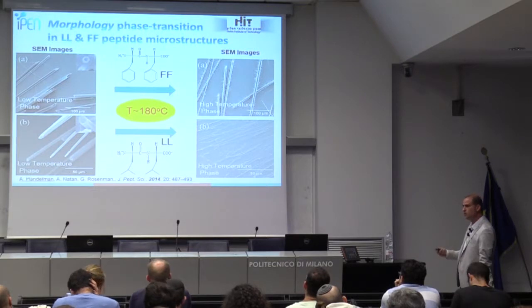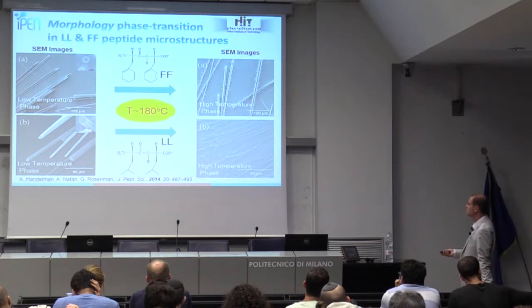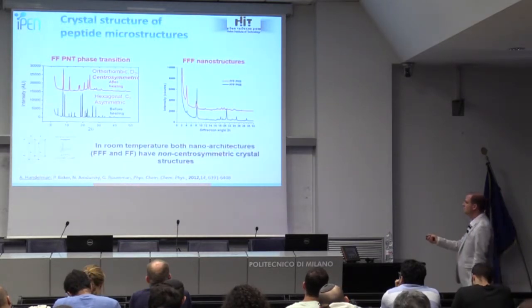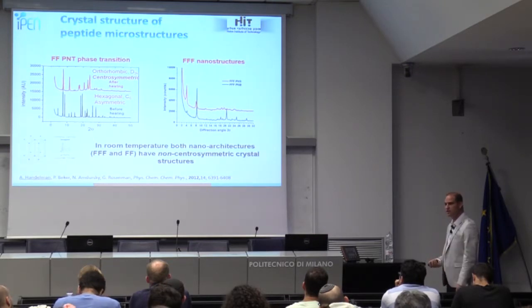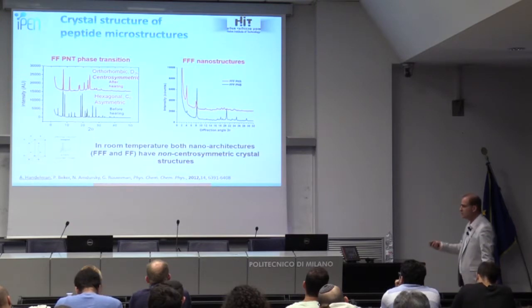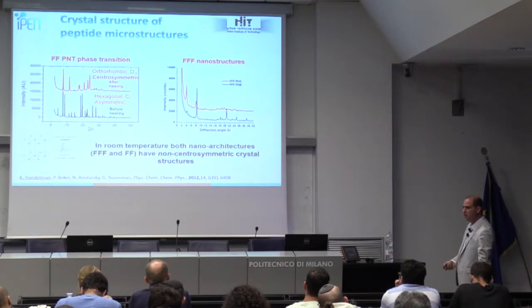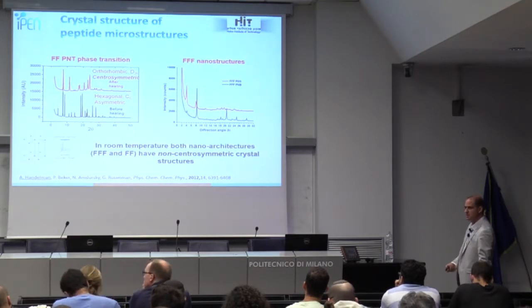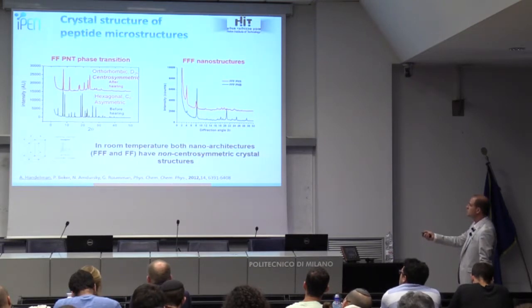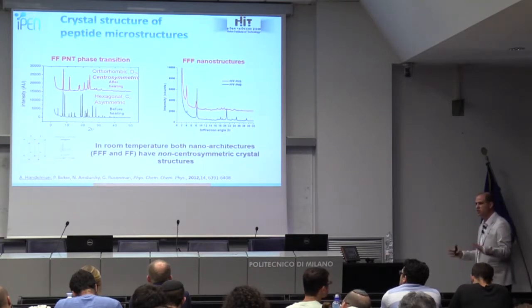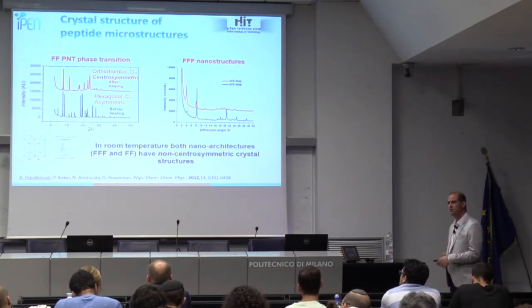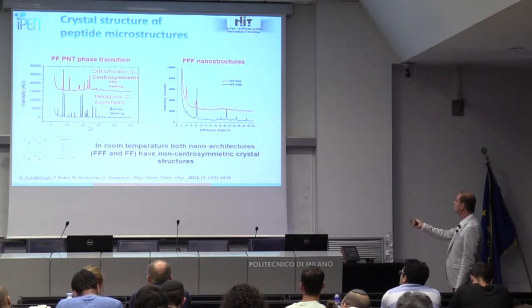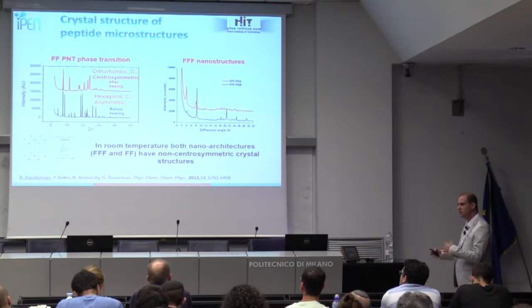So we wanted to see what happens during thermal inducement. First we measured X-ray diffraction, XRD, to investigate the crystalline structure of these peptide architectures. As you see here, before heating, we have an asymmetric, non-centrosymmetric crystalline structure, which is a C6 point group. And after heating, the crystalline structure changes into orthorhombic D2h with centrosymmetric. I will talk soon about what centrosymmetric and non-centrosymmetric mean, but this is the first big change that heating induced in these structures. For the triple F nanostructure, it's a little bit different, but there is also some kind of change.